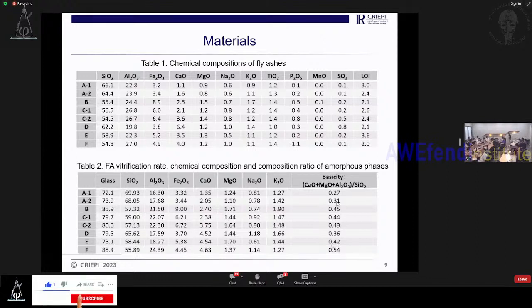The silica content is from about 55% to up to 66%, and calcium content is very low. It's a siliceous type of fly ash. Table 2 shows the glass ratio, the amount of glass in the fly ash. It's noted as the vitrification rate.